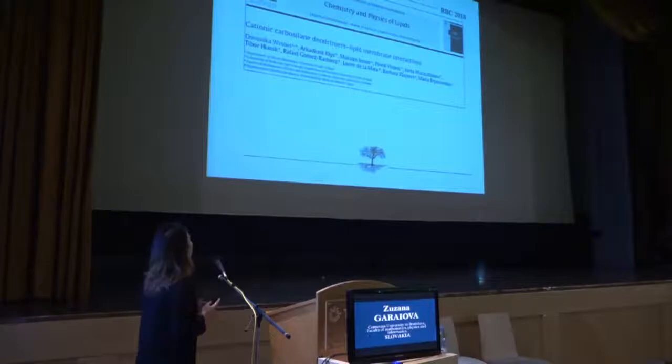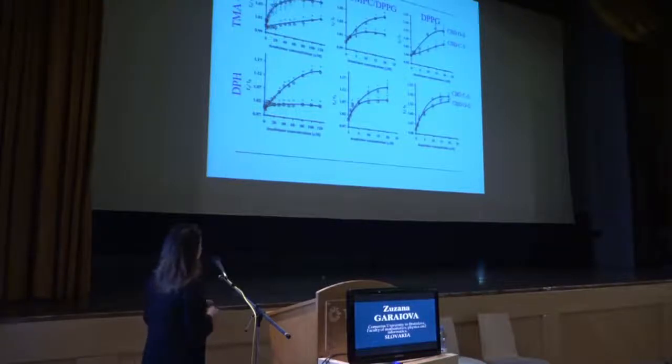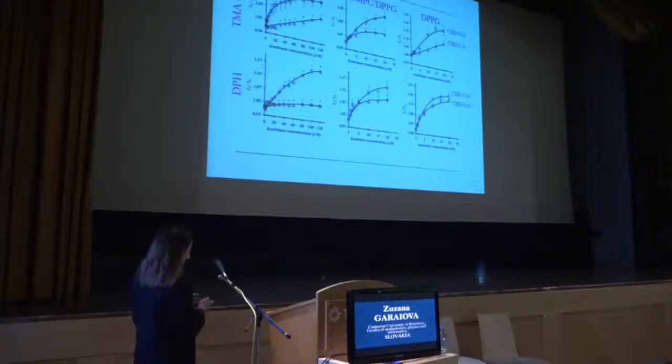And the methodology procedure, so we were creating monolayers using Langmuir-Blodgett trough. So we were creating monolayers by spreading lipids on an air-water surface at a certain surface pressure, which was approximately 30 millinewtons per meter. That's the physiological value of normal cells. And then through a small aperture inside the measuring cell, we injected our compounds, and we were checking changes in that surface pressure.